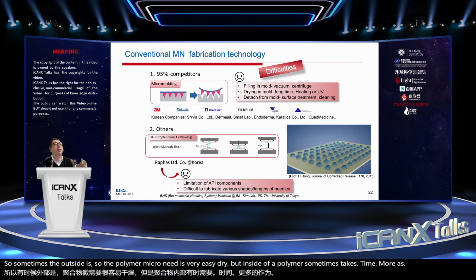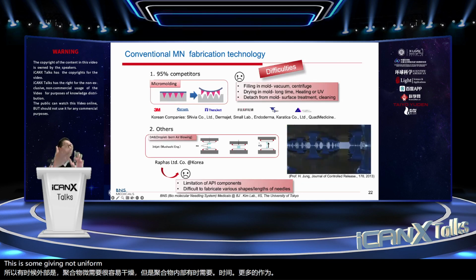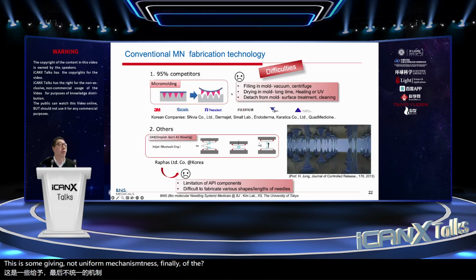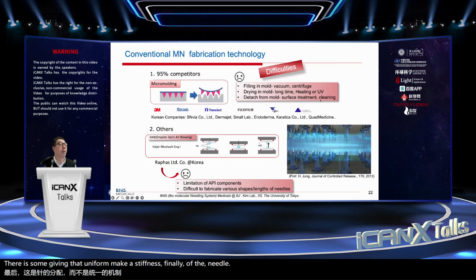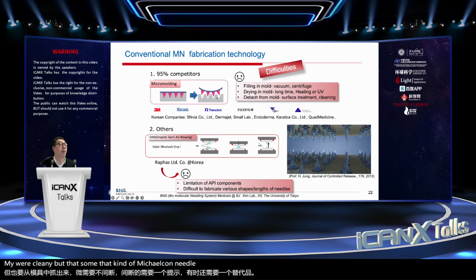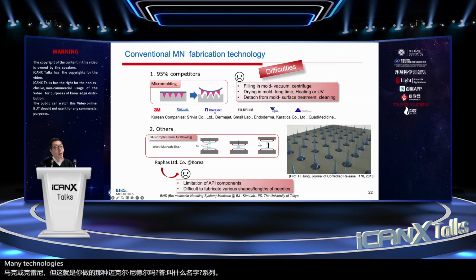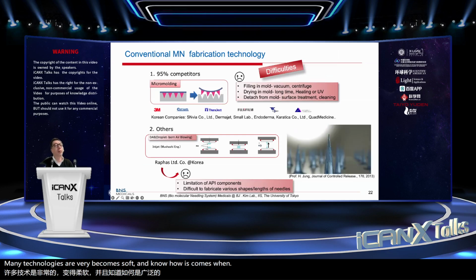This affects giving a uniform mechanical stiffness to the needle in the end. But also there is detaching the microneedle patch from the mold without breakage of the needle tip. Sometimes it needs a substrate mount or cleaning, but for that kind of polymer microneedle, many technologies and know-how have become stocked up and are developing well. Now many people are already conventionally aware of that.